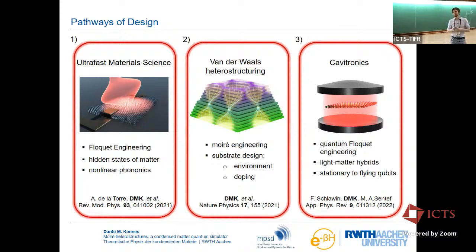But we do different things along these three pillars that you see. The first pillar is to use non-equilibrium external stimuli to control quantum material properties. So that is prototypically, let's say, blasting a system with a strong laser, and then the electromagnetic forces onto the system can effectively alter the properties that the crystal exhibits. One prominent example is that you have a periodically modulated field when the laser is on, so you're shaking your system periodically, and then you can show that that effectively alters the Hamiltonian that the system feels, and that of course will lead to different material properties. And that goes under the name of Floquet engineering and has become quite famous in the field.